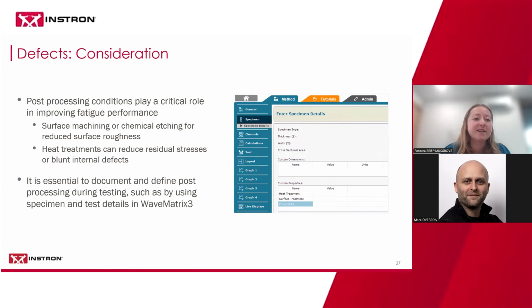Well, the first, as I mentioned, post-processing can play a really critical role in improving that fatigue performance. So people will often consider surface machining, and this is often defined in perhaps the standards you might be using for testing. They will define a particular surface roughness, or indeed chemical etching for reduced surface roughening, and also heat treatments. It's very common to see people using heat treatments on additively manufactured parts to reduce those residual stresses or perhaps blunt the internal defects and improve fatigue performance.